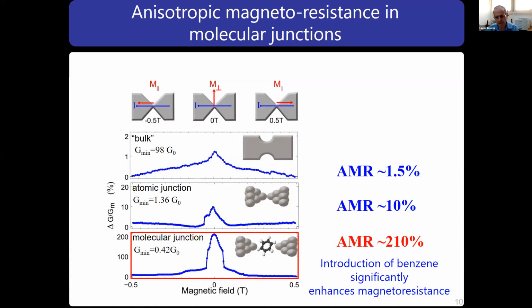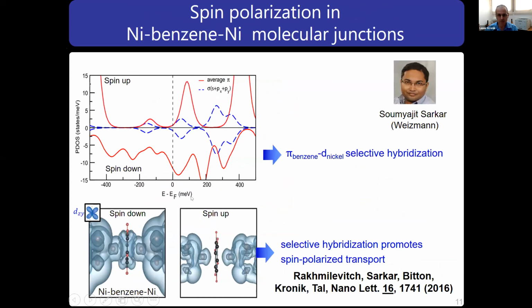Now, a direct computation of anisotropic magnetoresistance is not so simple because it involves various assumptions about the spin-orbit coupling and, more importantly, various scattering mechanisms. So we didn't go there, but we didn't need to because we could get the answers that we were looking for just by looking at the spin-polarized density of states. So my postdoc, Soumyajit Sarkar, calculated the density of states for this junction. What you see on the top figure is the partial density of states for spin up on the top and spin down as a mirror image on the bottom.